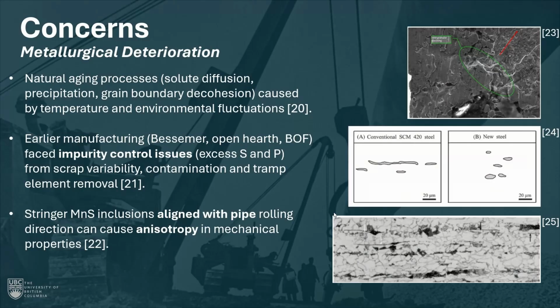So these are just some images showing specifically, in the middle image, we can see the banded or elongated stringer sulfide inclusions, compared to new steel where they add calcium, which helps essentially, I'm not too familiar with the process, but it essentially breaks up those sulfide inclusions into globular, smaller size, which are then more dispersed within the steel lattice.